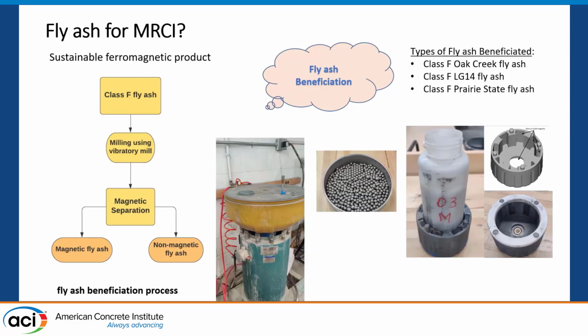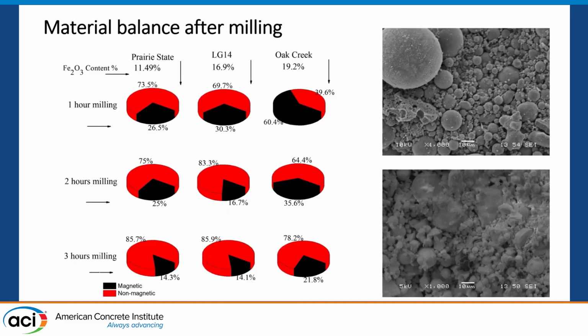Well, first of all, if we look for magnetic inclusions in fly ash, well, I have this picture, right? So basically, a cenosphere would contain magnetic portions and non-magnetic portions. I don't think the magnetic material is sitting as a separate grain. It's embedded into the structure, the alumosilicate matrix. Consider a muffin, and you have these perfect grains, or berries, embedded into the structure. How to extract them? You need to break the structure down and have smaller chunks.